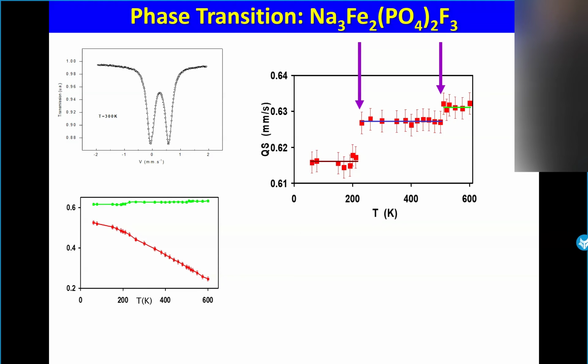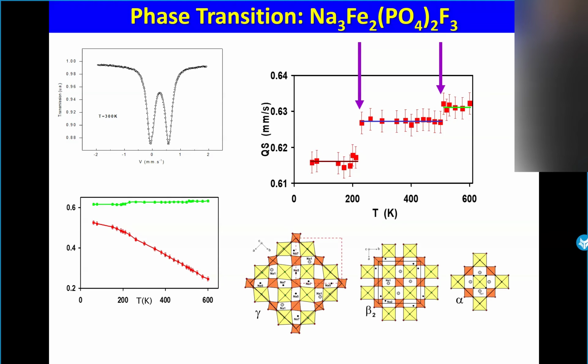Now the idea is to look at the structure. Of course, Mössbauer does not give information about the structural evolution, but it was supported by X-ray diffraction. It was possible to see that at high temperatures, in the change between the gamma and beta phase on decreasing the temperature, it was only a kind of octahedra that were not dancing samba, they were fixed. And the other phase transition was a change of one atom in the unit cell. So that means we are extremely sensitive to the environment. Okay?